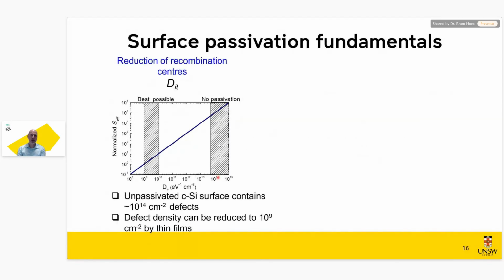And to explain this, we have to go back a bit to fundamentals. If we look at surface recombination, it's governed by two different processes. First you have interface recombination, where the recombination rate, in this case the surface recombination velocity, or the surface saturation current density as well, is basically equivalent. It just depends linearly on the number of defects you have. In this case it is quantified by the interface defect density, which for the passivating films that we use is around 10 to the 10 defects. So it doesn't mean you have 0 defects. You just have a lot fewer than if you would not do anything. If you don't do anything, you have roughly 10,000 times more defects.